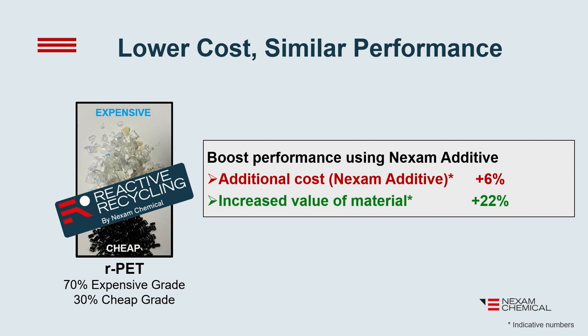And if you do the cost calculation, you can see that the additional cost by putting in our additives is about 6% of the material cost. However, the increase in the value of the material is in excess of 20%. So what we see here is we can actually take cheaper material and we can build value for our customer using our product.